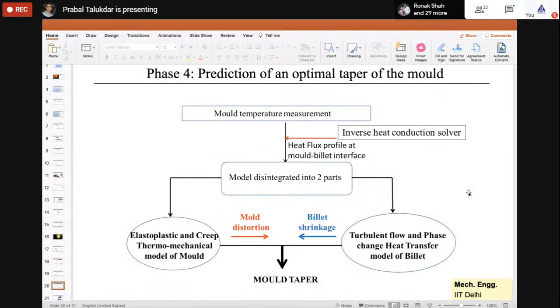This was the overall sequence of our problem. The first thing, we get mold temperature measurements from the industry. Then we have used an inverse heat conduction model. Using the inverse heat conduction model, we have predicted the heat flux profile at the interface of mold and billet.